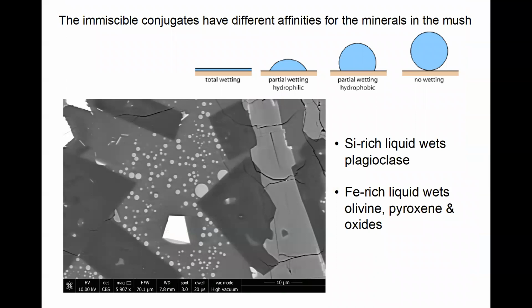Now, what's interesting, and I think what is driving all of this, is the fact that these immiscible conjugates have different wetting properties. So this is just an image of an experiment. The silica-rich liquid, which is this grey one, wets plagioclase preferentially. It wants to sit next to plagioclase, whereas the iron-rich liquid wants to sit next to oxides, obviously, and other mafic phases. So you can see here, this is the iron-rich liquid. Look at this low wetting angle here. It's hugging really close to that oxide grain. Similarly, these blobs here, the iron-rich liquid, yes, it's sitting on the plagioclase, but it's got a high wetting angle. It doesn't want to be there.